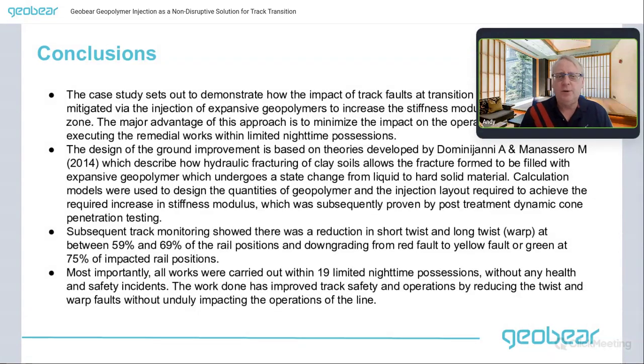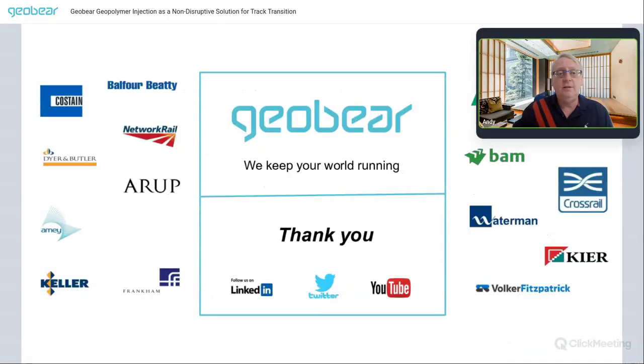Subsequent track monitoring showed there was a reduction in short twist and long twist warp at between 59 and 69% of rail positions, and downgrading from red fault to yellow fault or green at 75% of the impacted rail positions. Most importantly, all of the work was carried out within 19 limited nighttime possessions without any health and safety incidents. The work has improved track safety and operations by reducing the twist and warp faults without unduly impacting the operation of the line. And that is the end of the presentation.